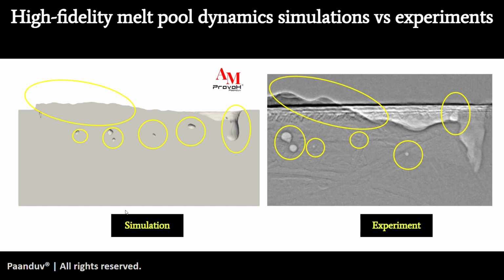Again, I want to highlight the pore formation. I mean, that is something, and the hump formation. So all the mass which has ejected out from the melt pool has been deposited over the top, as you can see on the experimental image on the right hand side in the big oval, and then on the left hand side again you can see a lot of deposition of material behind the melt pool.